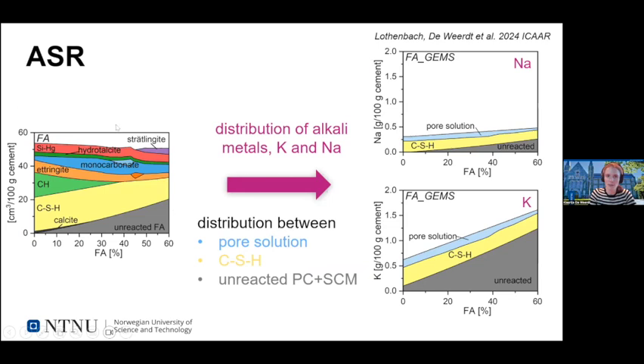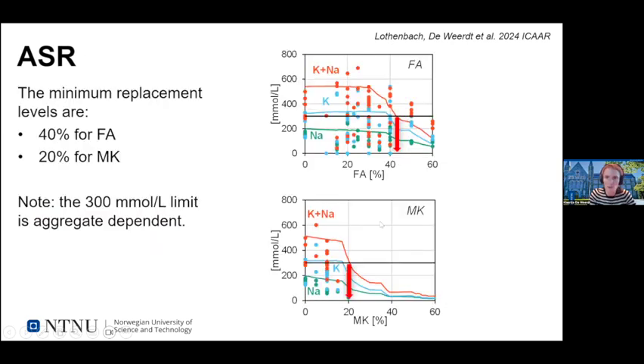And here I show the example for fly ash, and I split up the effect for sodium and potassium. When we look at, for example, potassium, we see that a large part of the potassium is in the unreacted fly ash, part is in the CSH, and part can be found in the pore solution. And when we then plot the potassium and sodium concentration in the pore solution as a function of the replacement level, that's what I did here.